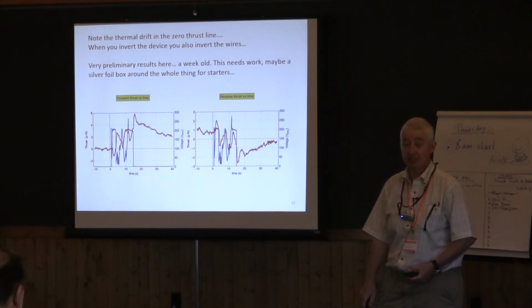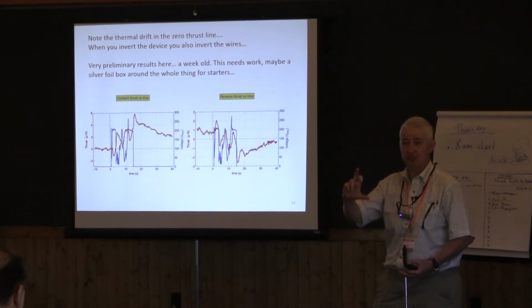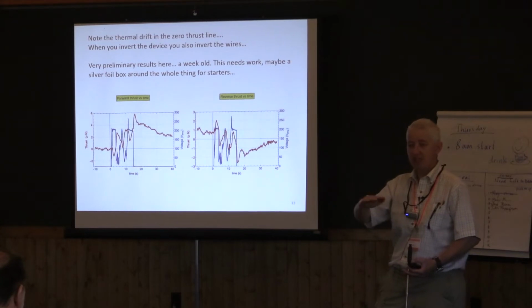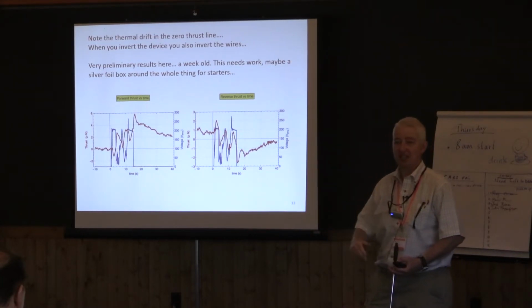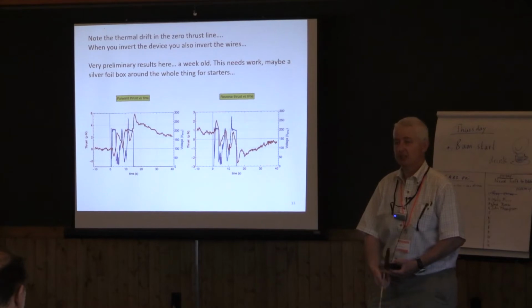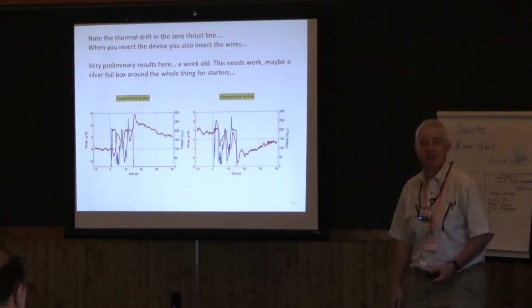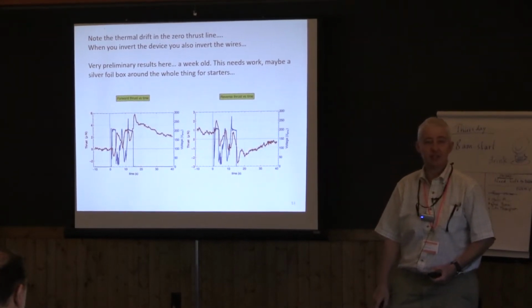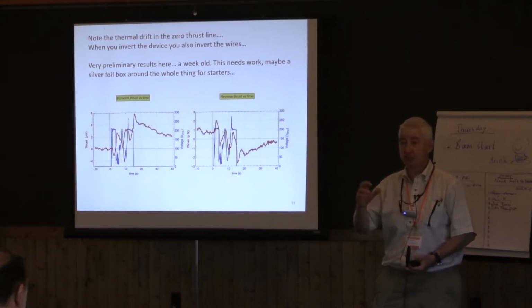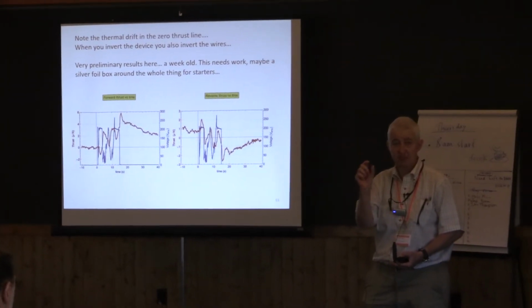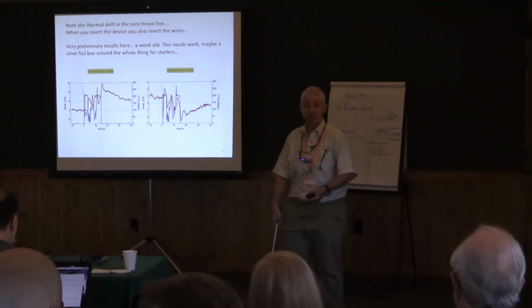It could be the brass masses absorbing some of that heat, because now I've got the same voltage going to 2 drives, and the brass seems to slowly heat up and then slowly decay again, where the aluminum heats up more rapidly. So I'm not sure. Check how much resistance there is in the contacts that the wires are making with the outside. It's very easy to get dirty contacts. Yeah, and of course now there are more contacts because I had to put an extension on the wire, so the little contact clips may be heating up possibly. So I'm going to have to check that. There's a few things I can check.